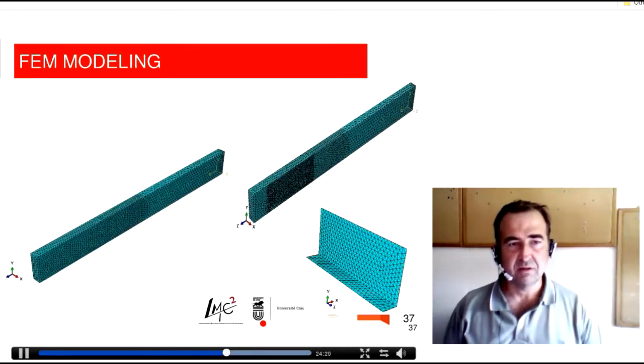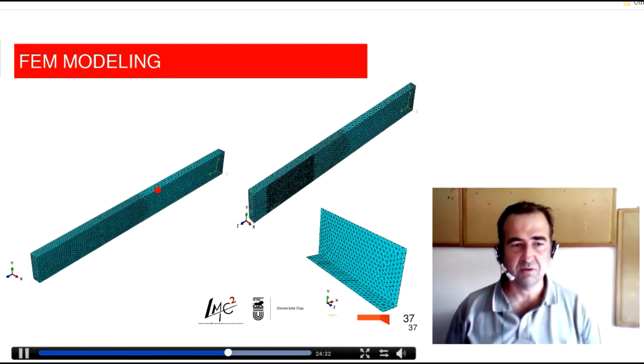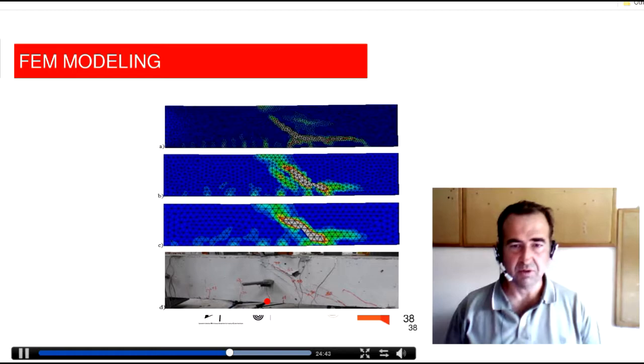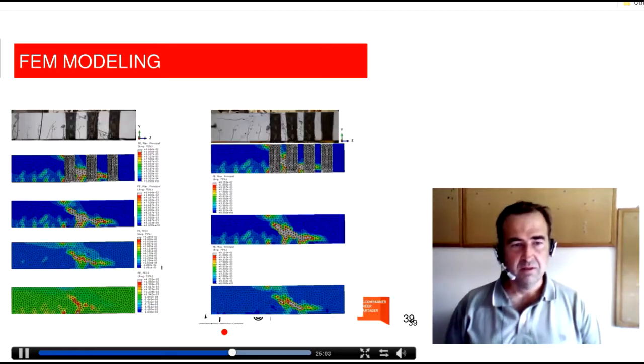To compare this, we developed some finite element modeling using plates for the composite area. The reinforced concrete beams were modeled using ANSYS software and with internal reinforcement and smeared concrete crack approach. And in this case, we were able to model the crack, which was more or less very comparable to the one obtained experimentally. And you can observe here also the large strain we have with the experiment. So with the strips, again, you can have here the comparison between the experiment and the modeling. It means that it allows to get the high level of stress we have.